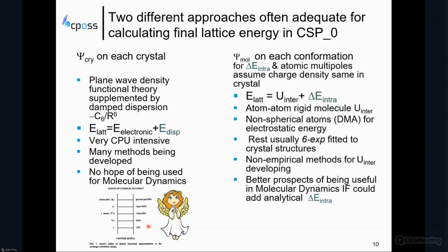Our approach that started 3 decades ago is just to do the wave function calculation on the molecule. So you use the quantum mechanics of the molecule in each conformation to get the intramolecular energy penalty of deformation of the molecule from its lowest energy conformation, and also the atomic multipoles that model the charge density at that conformation, which we can use to calculate the electrostatic contribution to the dominant intermolecular energy of the crystal. So we've got non-spherical atoms having distributed multipole analysis for the electrostatic energy. And this proves crucial for modeling the orientation dependence of the hydrogen bonding and pi-pi electron stacking, etc.